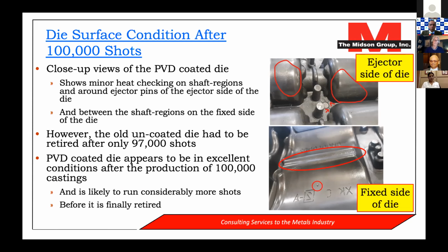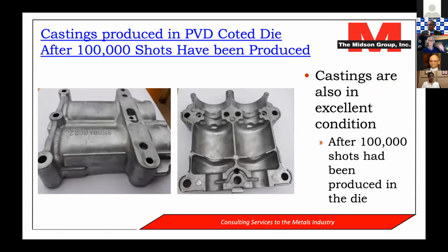And again, as a reminder, the old uncoated die had to be retired and replaced after only 97,000 shots. So the PVD coated die does appear to be in excellent condition after the production of 100,000 castings, and is likely to run considerably more shots before it is finally retired. This is showing the pictures of the castings produced in the die after 100,000 shots. And because the die looks so good, it's not surprising that the castings also look very good, but they do. And again, here are pictures of a casting produced in the die after 100,000 castings had been produced.